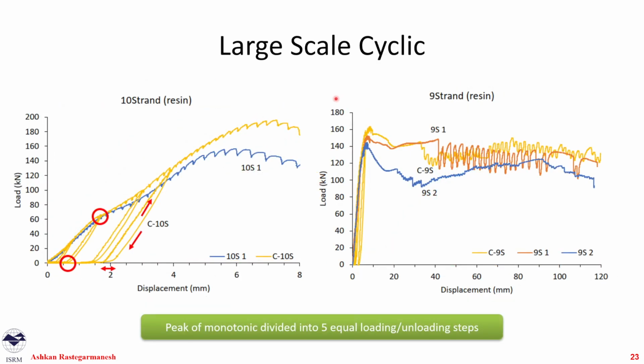For our cyclic testing, what we mean by cyclic testing in this research is that we did the monotonic testing. We got the peak value of that. We divided by 5, and we made 5 equally spaced loading and unloading cycles. And these are the unloading and loading cycles that we see. Again, our aim was to see what happens over the life of our structural element when we have changes of stress or environment in the mine or underground space in tunnels.